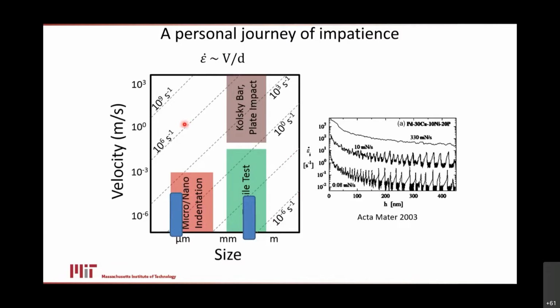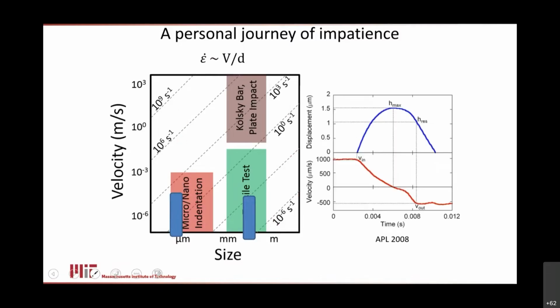scale mechanical testing and push it to even higher rates. And so one of the projects I worked on there in my first 5 or 6 years was to help develop what is now known as the dynamic indentation test. And dynamic indentation is essentially nano indentation, but you attach it to a pendulum and give it a little bit of a swing. And so now you indent something, but you're able to measure the velocity of the indenter as it strikes the substrate and then as it rebounds from the substrate. And with that kind of technology, you can push this up a few more orders of magnitude. And now, at the micro scale, you're measuring things that have strain rates comparable to a Kolsky bar or a flyer plate impact or something like that. So you get genuine high rate data at the micro and nano scale.